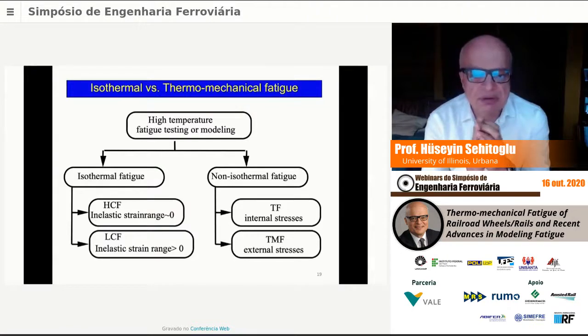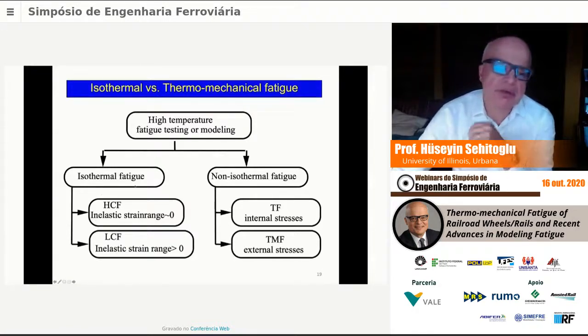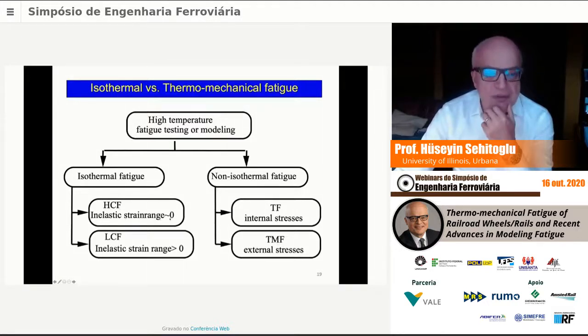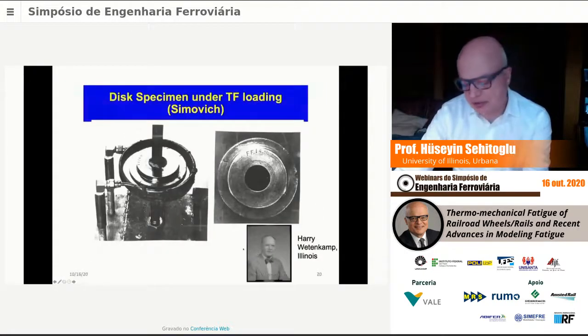So there's terminology in high temperatures. We call isothermal fatigue constant temperature. Non-isothermal fatigue means either thermal fatigue or thermomechanical fatigue. Thermal fatigue means there are no external forces applied. The stresses are internal because of temperature gradients. In thermomechanical fatigue, we are applying external forces, external stresses, so that has a mechanical load as well. High cycle fatigue means the inelastic strain range, at least measured at the macro scale, is roughly zero. In low cycle fatigue, the inelastic strain range is greater than zero. These are the definitions that people often use.